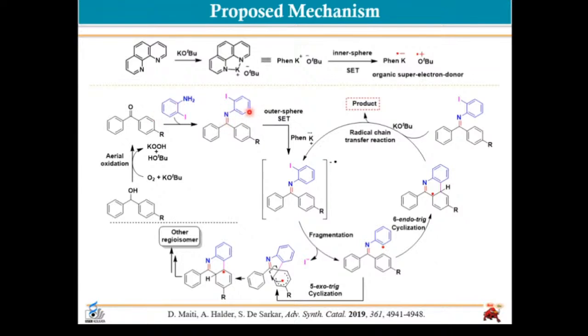Once you form this imine, we have this organic super electron donor already present in the mixture. Then there is a single electron transfer, and this will go because the imine becomes a little bit electron deficient. It will accept this electron in the LUMO, and once you push the electron here, this carbon-iodine bond is a bit labile, with homolytic breakage giving I minus and a radical. Once this forms, this aryl radical is reactive, it will intramolecularly cyclize and form this new radical, and ultimately this transfers one H dot and forms this product. The rearomatization here, nothing else.